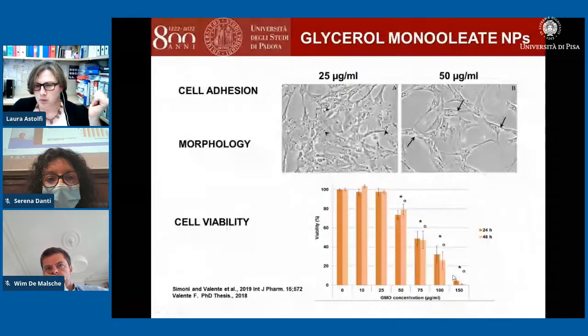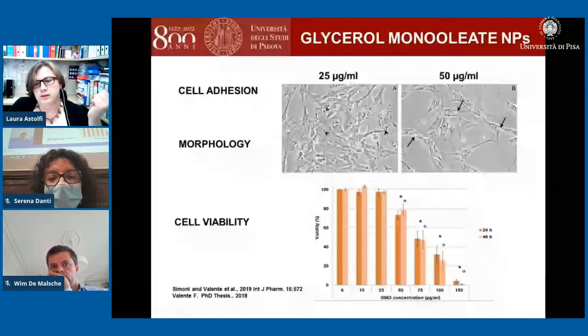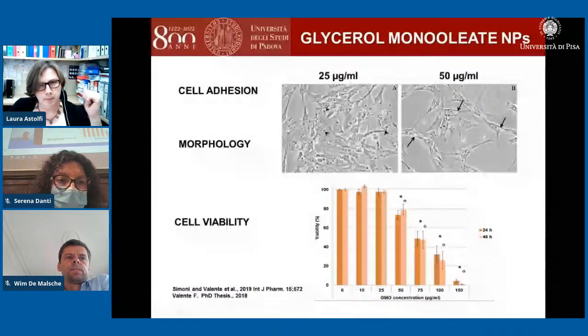And if we look at the morphology, with 25 microgram per ml we have a good condition of the cells, because the shape stays polygonal and the nuclei are in good condition. When we test the 50 microgram per ml of nanoparticles, you can see that we have a thinner shape, so the cells start to be stressed, and we have a lot of microvesicles, maybe lipid vesicles, inside the cell.